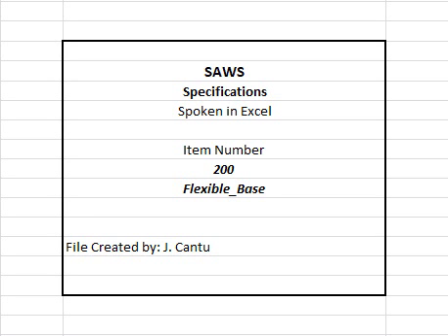Just prior to the placing of any succeeding course of flexible base or surfacing on a previously completed course, the density and moisture of the top 3 inches of flexible base shall be checked, and if the test shows the density to be more than 2% below the specified minimum or the moisture content to be more than 3% above or below the optimum, the course shall be reworked as necessary to obtain the specified compaction and moisture content.